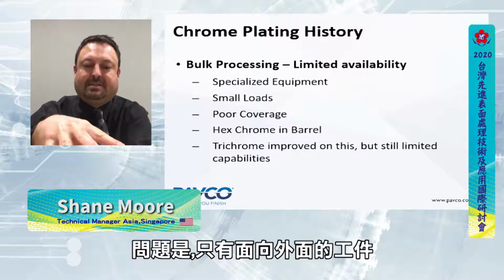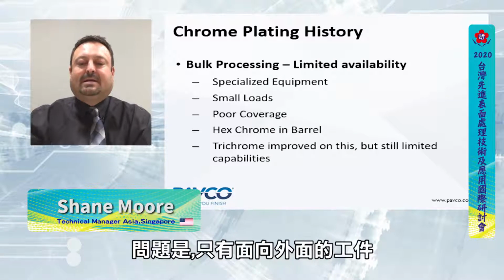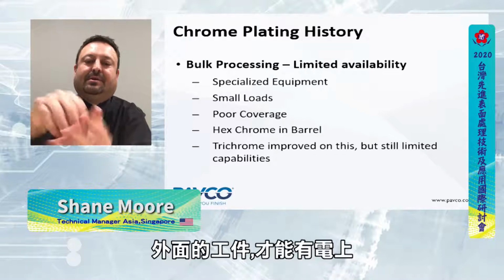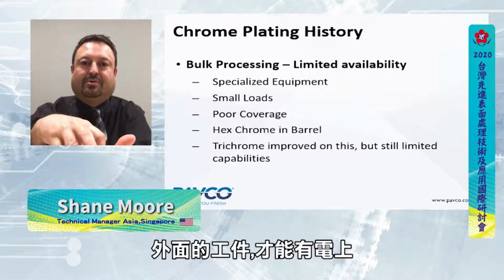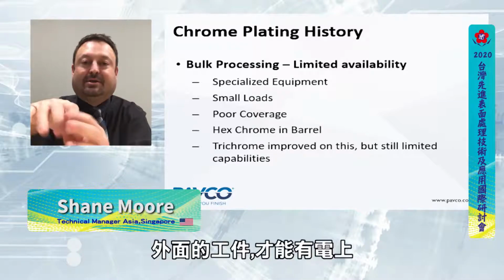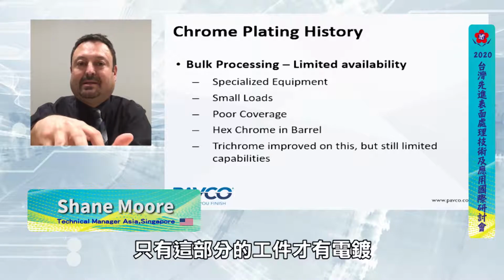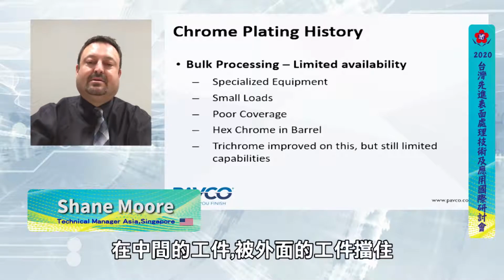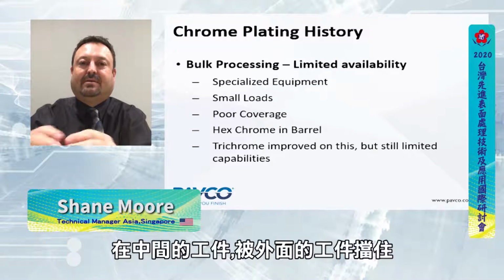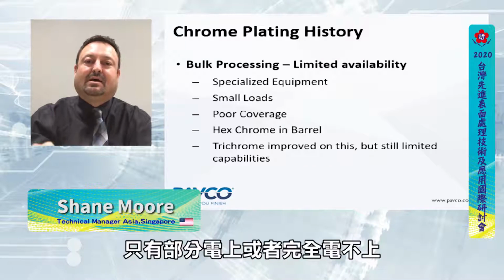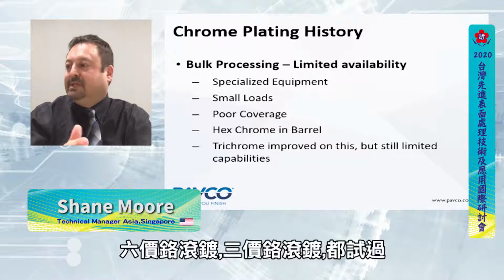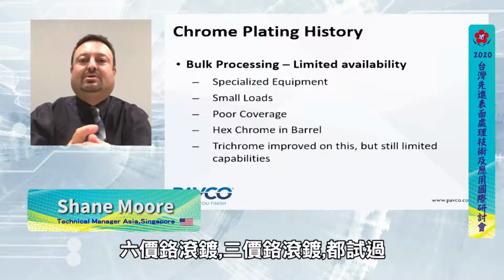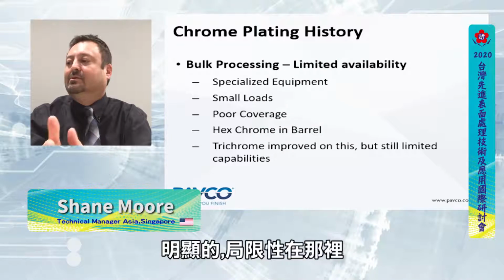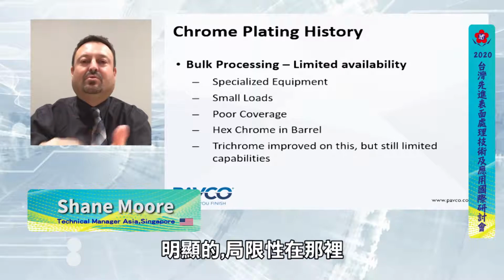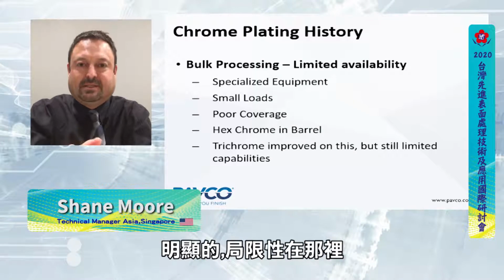And the problem with this is that only the parts on the outside of the basket, in the outer part of the load, were able to see the current. So that's the only parts that really got plated. The parts in the center were kind of shielded by the outer parts, so most of those got very little to no plating at all. It had been tried. Hexchrome had been tried in a barrel. Trivalent chromium had been tried in a barrel. It was only able to be successful when you did this, and you can obviously see the limitations involved there.